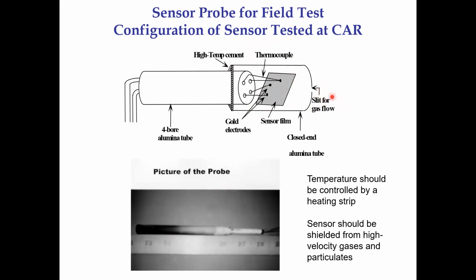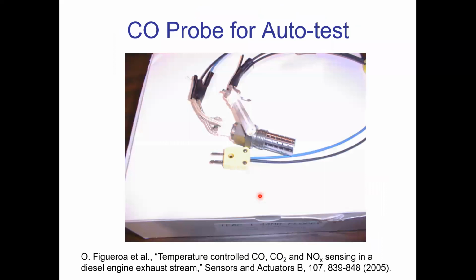So you can see the actual package, then we cover it with a ceramic tube like alumina with a slit for the gas to get in. You can see even with the slit, the protective layer gets blackened by carbon soot in the end. So the engine environment is really a very dirty environment.